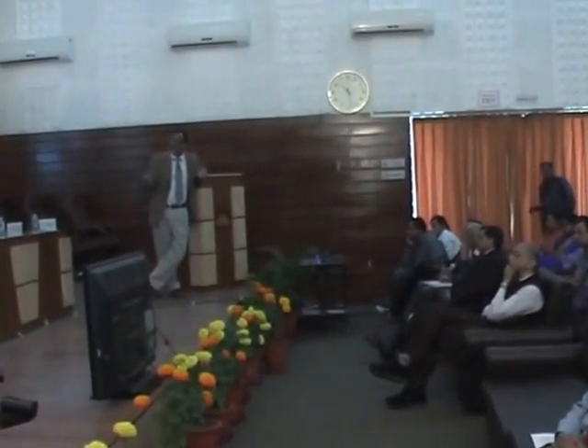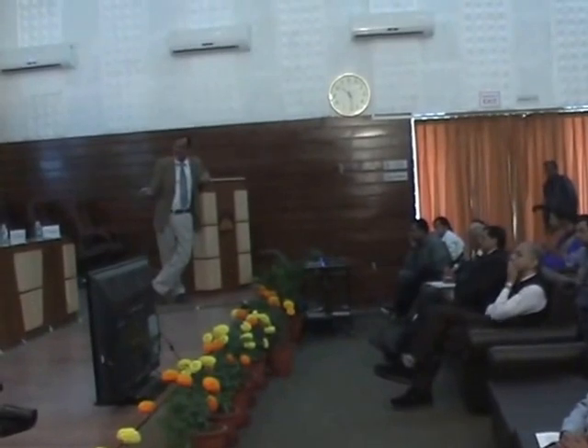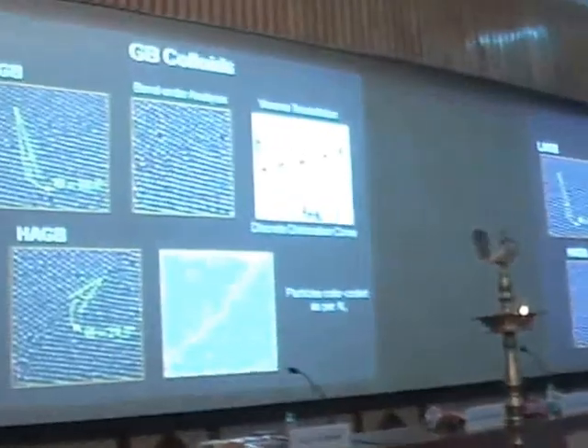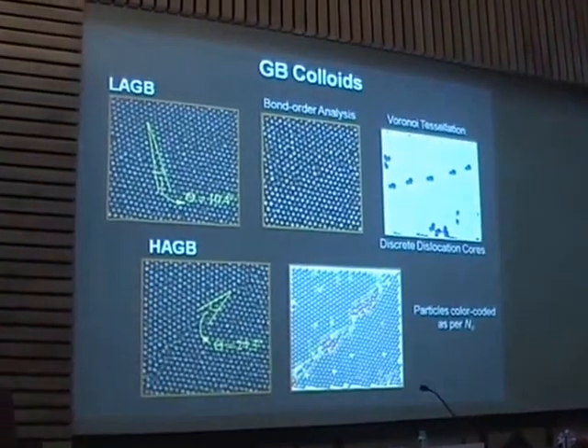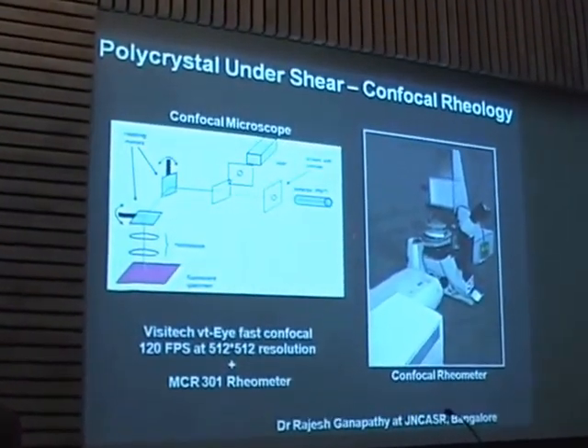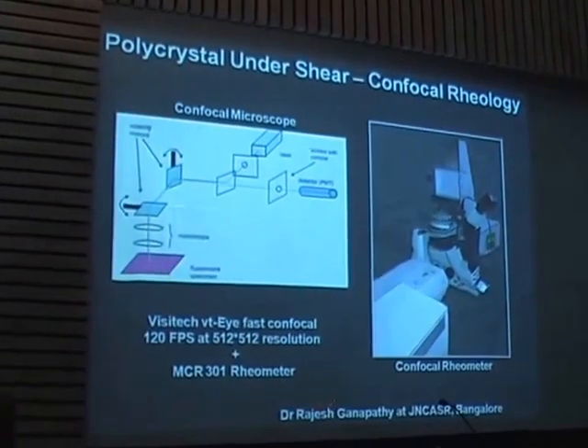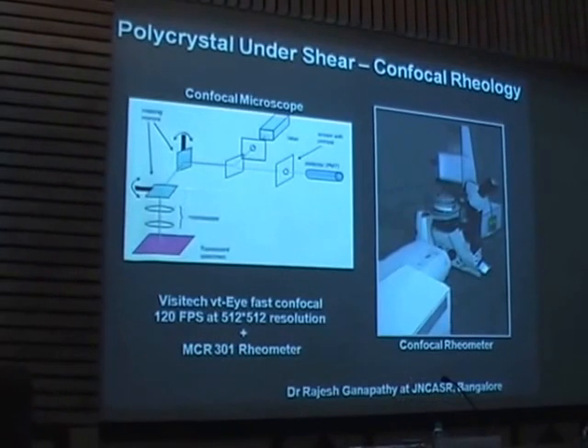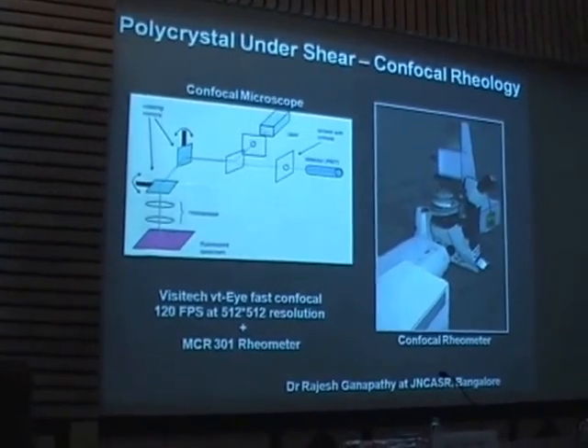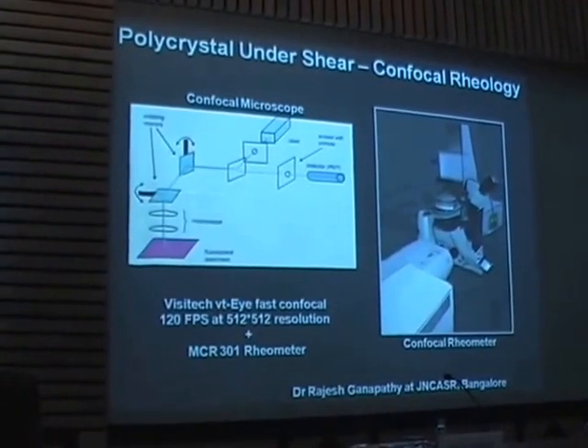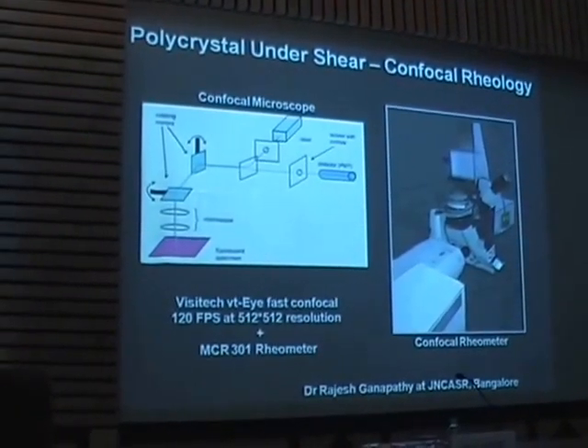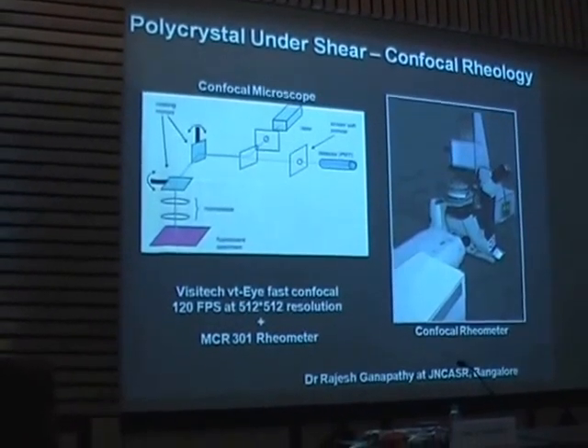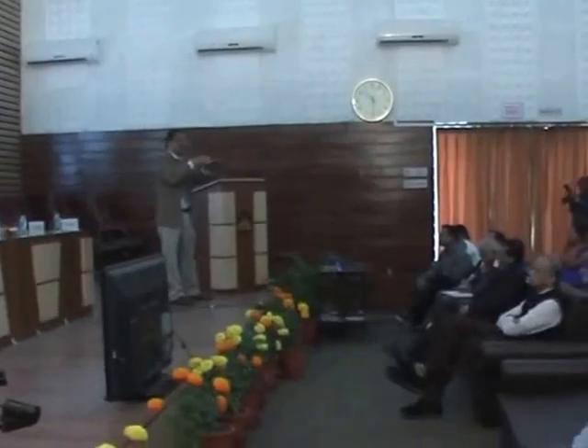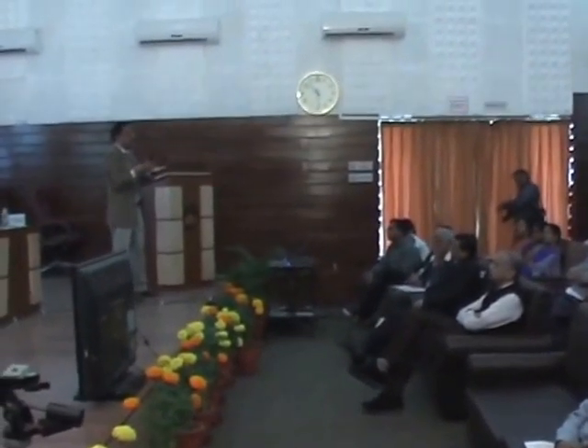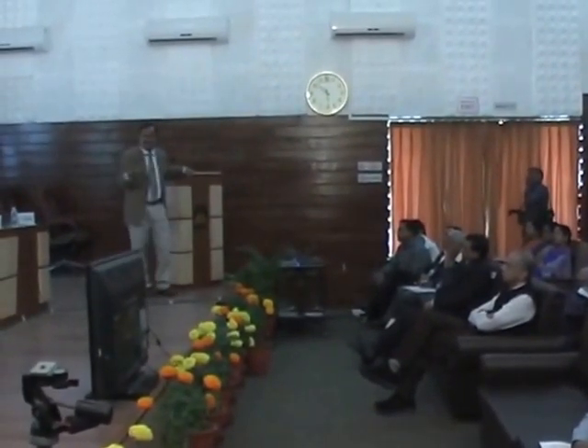We can identify grain boundaries by appropriate mathematical constructs, by looking at the neighborhood and how they are correlated, and then we can find out how these grain boundaries behave when you shear it. Now this is a very beautiful experiment set up by Dr. Rajesh Ganapathy at JNCASR. This is a very difficult experiment. Here what he has done is set up the whole rheometer on a confocal microscope. So when it is being sheared, you can do confocal microscopy. There are very few setups in the world which can do that, and this allows us to do the shear and look at the microscopy at the same time and get very detailed static and dynamic properties.